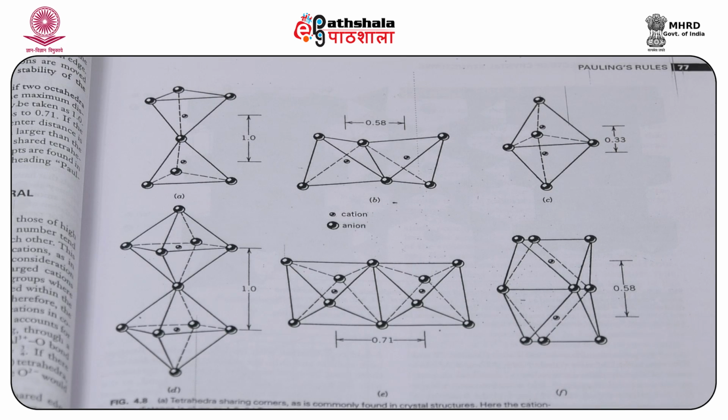This accounts for the lack of AlO4 structures and tetrahedra bonding through bridging oxygen in many silicates. The Al3+ bonded to oxygen in tetrahedral coordination has an electrostatic valence of 3/4. If there was a bridging oxygen between two AlO4 tetrahedra, it would mean 2 × 3/4, which is equal to 1.5, and the O2- would not be satisfied.